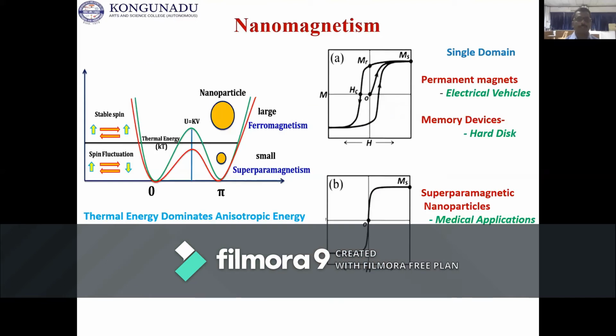So what happens in the superparamagnetic region? When particle size is reduced below the critical dimension, thermal energy dominates the magnetic anisotropy energy. So due to this, the spins of the magnetic materials fluctuate due to the temperature. So the magnetic spins are unstable. So you call it a superparamagnetic nanoparticle, as superparamagnetism. When the magnet is in a single domain, that is above the critical dimension, you have a strong hysteresis loop, where you can have a large coercivity and high magnetic remanence.